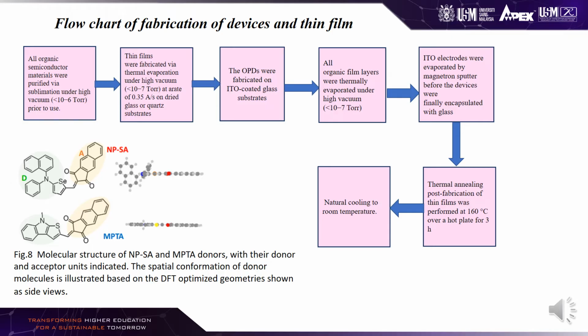This is the flowchart of fabrication of devices and thin films. The first step is that all organic semiconductor materials were purified via sublimation under high vacuum, lower than 10 to the power of -6 torr, prior to use. Then the thin films were fabricated via thermal evaporation under high vacuum, which is lower than 10 to the power of -7 torr, at a rate of 0.35 angstrom per second on dry glass or quartz substrates.